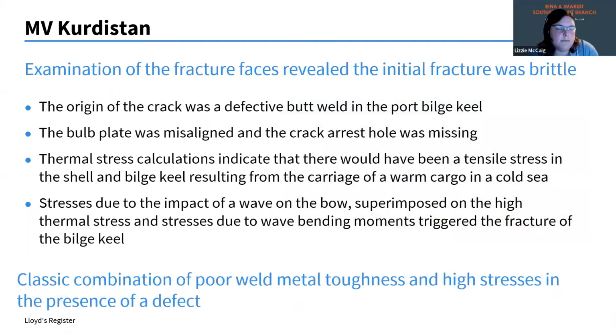Transport Canada investigated this, and they found that it was due to a brittle fracture. There was a defective butt weld in the port bilge keel. The bulb plate was misaligned, the crack arrest hole was missing, and thermal stress calculations indicated that there was a tensile stress in the shell and the bilge keel resulting from the carriage of the warm cargo in a cold sea. So you had this thermal stress issue.